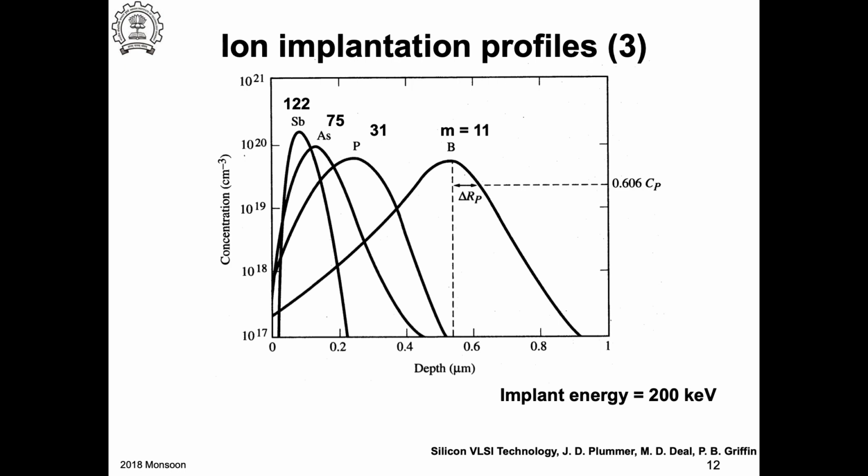the surface. On the other hand, if I take arsenic, for example, and draw a line here, it's again asymmetric, but there is a long tail towards the depth of the substrate. So this is important, and you can see the antimony is coming here. This is the peak, and again this part is broader than the center. But for boron, it's actually different.